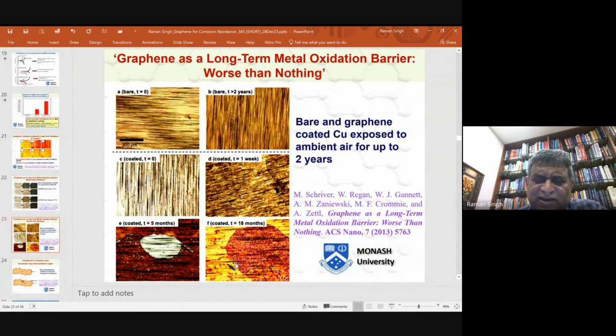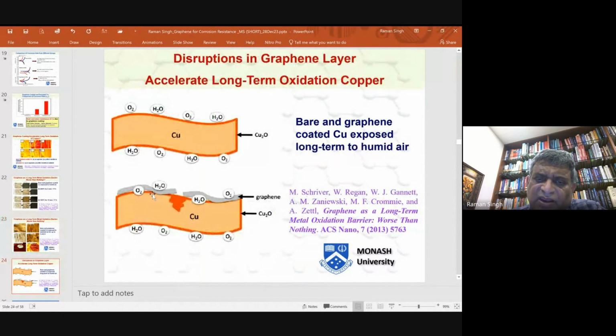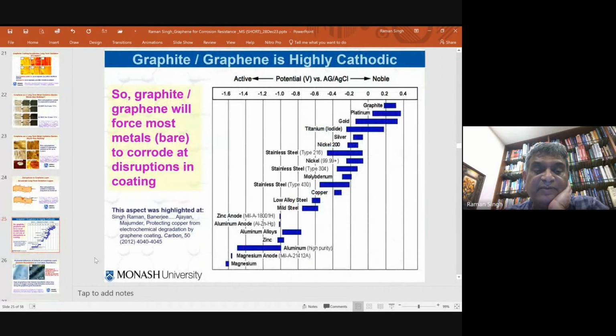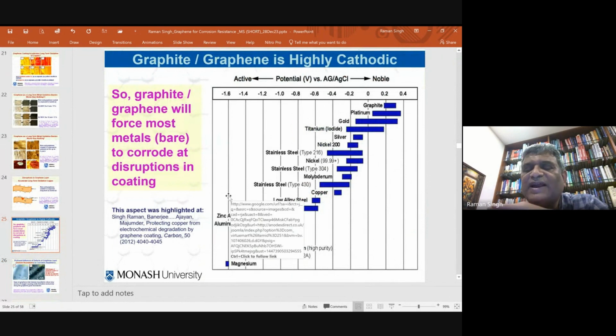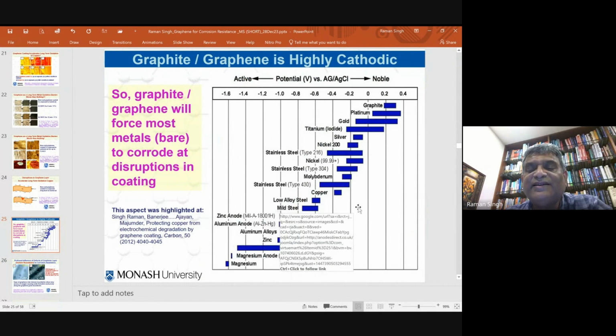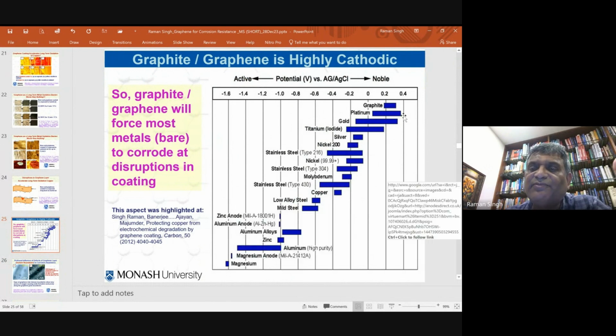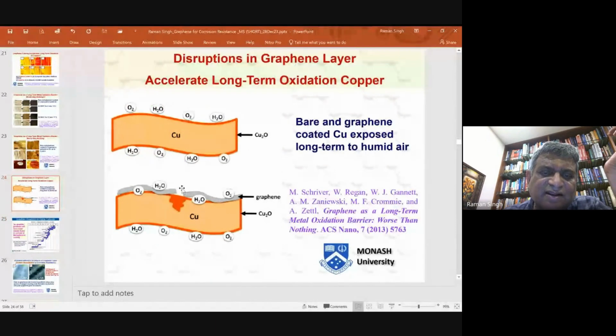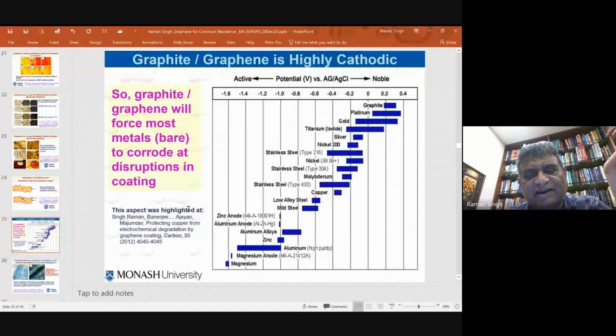The point that they were missing is that wherever graphene was intact, corrosion resistance was intact in those areas. Where there was disruption in the coating, corrosion was worse there. And they showed it in their schematic diagram that wherever you have breakage in the coating, corrosion was getting accelerated at that location. And which is not surprising at all. When we published our paper before them, we clearly mentioned that your coating has to be continuous. If you have disruption, at the location of disruption, corrosion will be higher for the simple reason that graphite is highly cathodic. If you attach it to anything, it will undergo corrosion. And that's what was happening here, that highly cathodic graphene was forcing the bare area to suffer corrosion at higher rate. So that was the reason. And we had mentioned that in our paper that we published earlier.